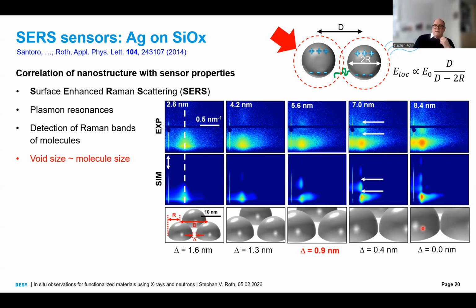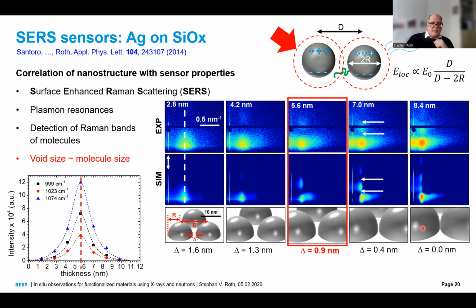Now, you can produce these samples ex situ and make this surface-enhanced Raman scattering experiment to check what the sensitivity is. Here we used one of the standards, I think it was R6G, rhodamine 6G, and then you measure the Raman signal as a function of the deposited thickness. So you make 10 samples with different thickness, you put your analyte on, and you find out that around a deposited silver thickness of 5.6 nanometers, you have a strong increase in the SERS signal.